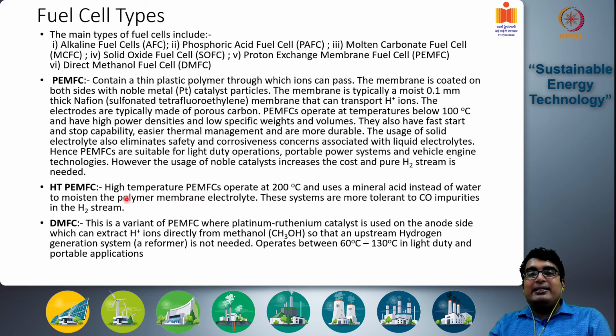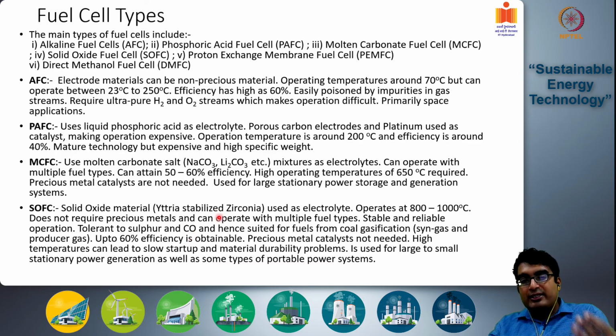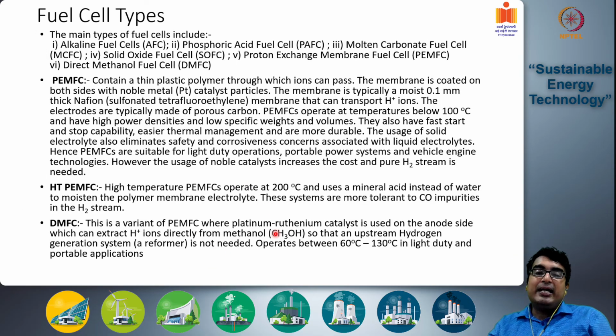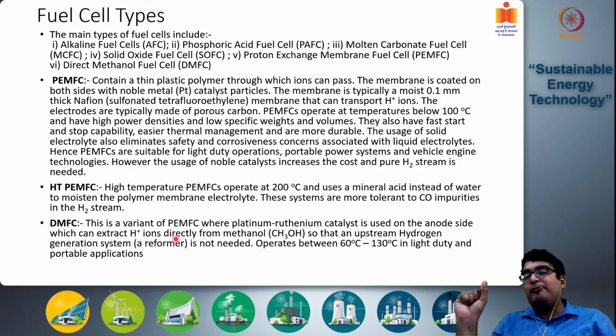The final one is the direct methanol fuel cell. As the name says, it can use methanol, CH3OH, the smallest alcohol, directly. In the other types of fuel cells, you can use carbon monoxide in some cases like SOFC systems, and some can use methane as well. This one can use methanol directly. It's a variant of the PEMFC, where a platinum ruthenium catalyst is used on the anode side, which can extract H+ ions directly from methanol. Instead of a platinum catalyst, it uses a platinum ruthenium catalyst, which works well to extract H+ ions from methanol, so that an upstream hydrogen generation system is not needed.